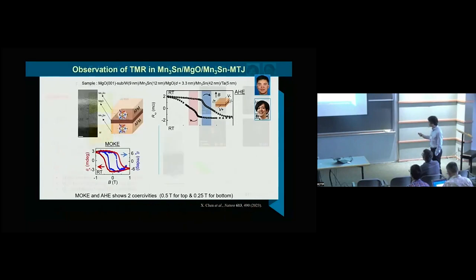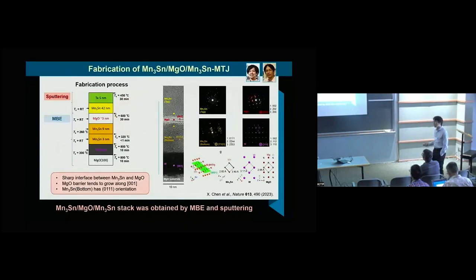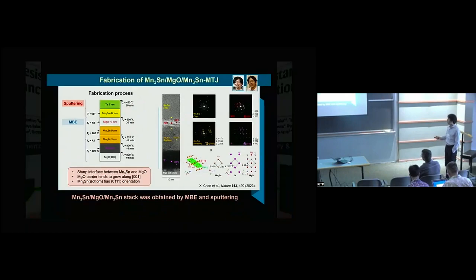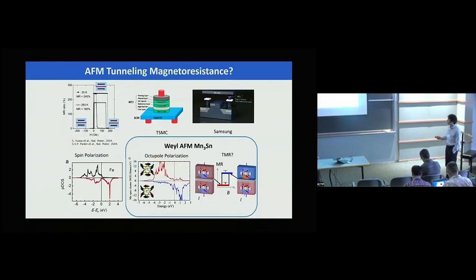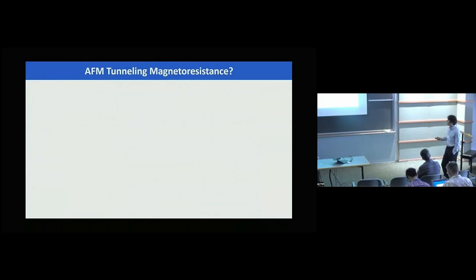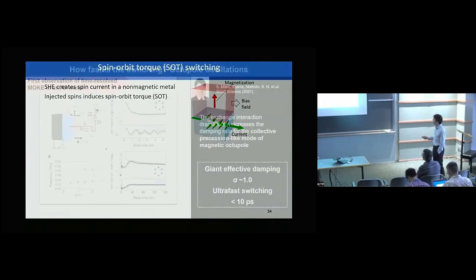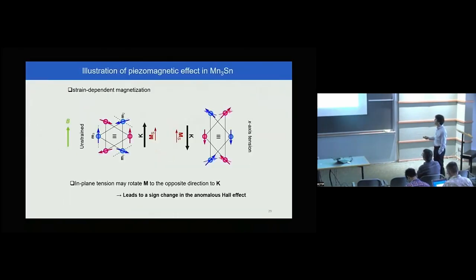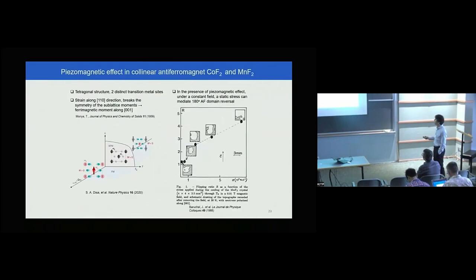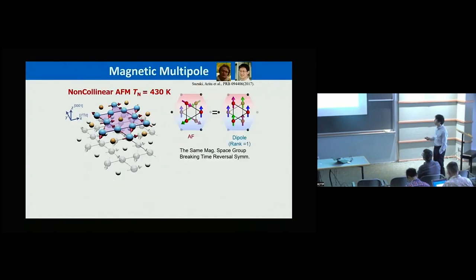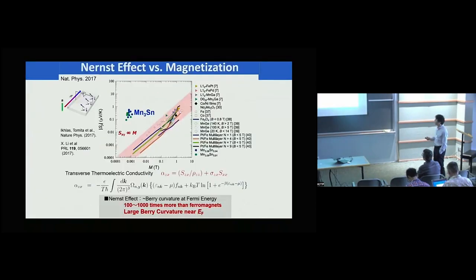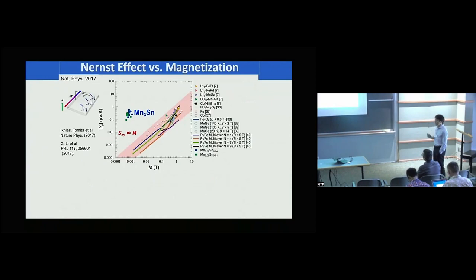Although diffusive, we actually see the signature of the Weyl points in the out-of-plane measurement, and also chiral anomaly, which I didn't show in this talk. I didn't prepare that slide, but we did see a chiral anomaly, which is fully consistent with the existence of Weyl fermions, and also the theoretical prediction for this planar Hall, and also the magnetoresistance.